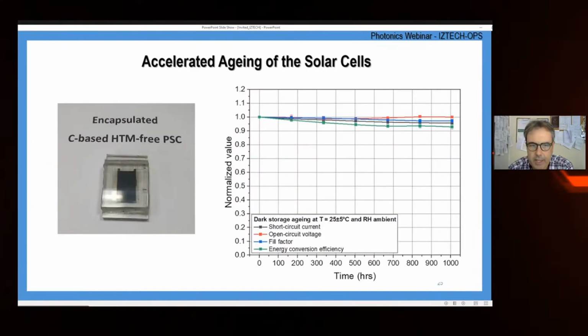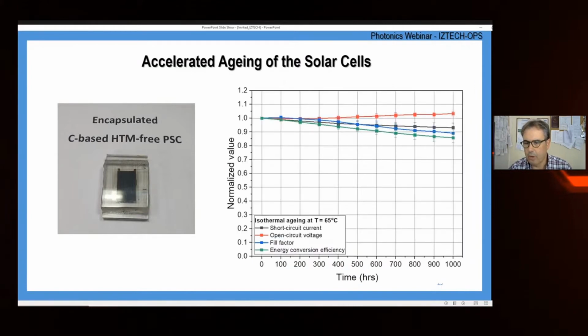As an example here, for an encapsulated device of small size, this is the result remaining for at least 1,000 hours in the dark. You will see that the stability of the device is pretty good, either the current or the open circuit voltage, the fill factor, and finally the conversion efficiency. Of course, we exposed it to